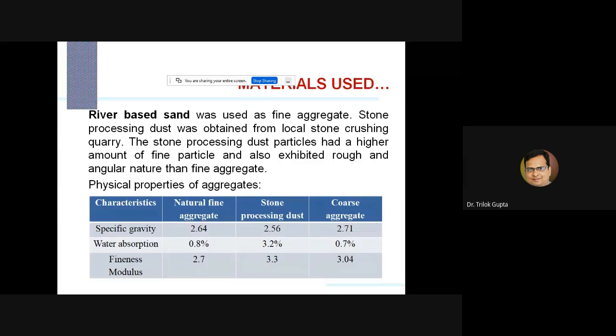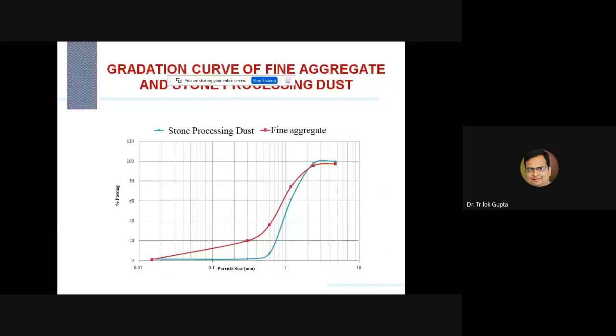All material was obtained from the local area. The natural fine aggregate was obtained from the nearby Kharka river, and stone processing dust was obtained from the local crusher plant, around 15 kilometers from the city, and coarse aggregate from the same plant. Water absorption was 3.2% for the stone processing dust as compared to 0.8% for the natural fine aggregate. That was high due to the presence of fine particles. Coarse aggregate had a normal water absorption of 0.7%, and the fineness modulus was 2.7, 3.3, and 3.04.